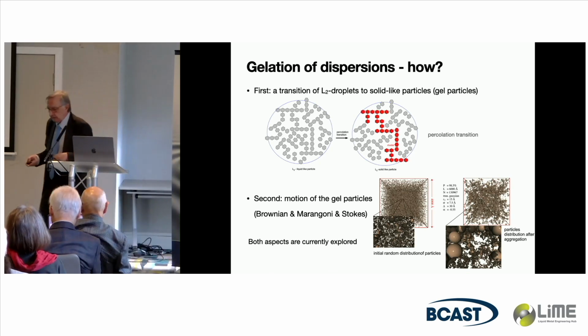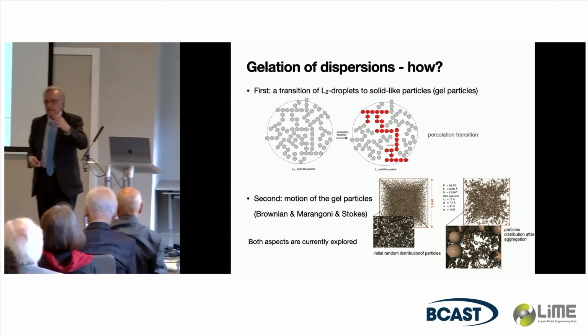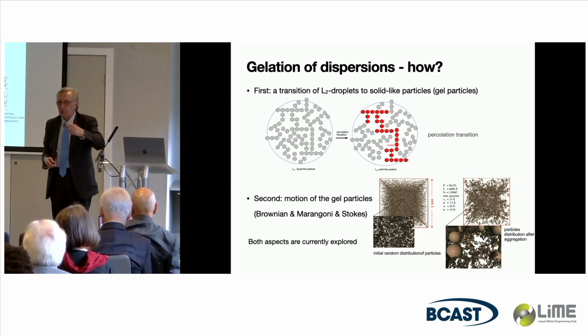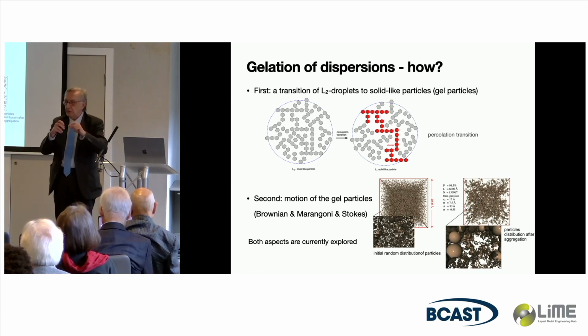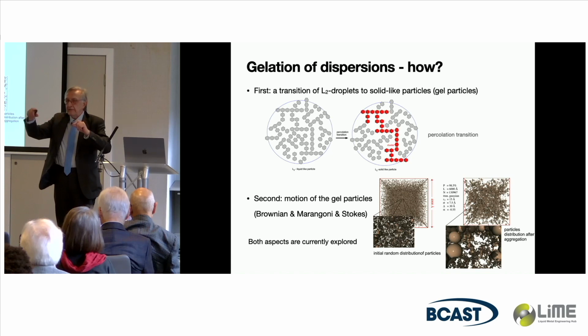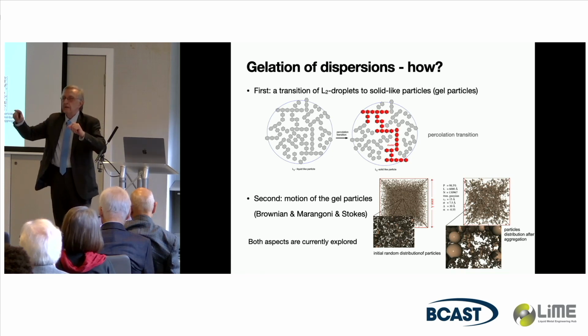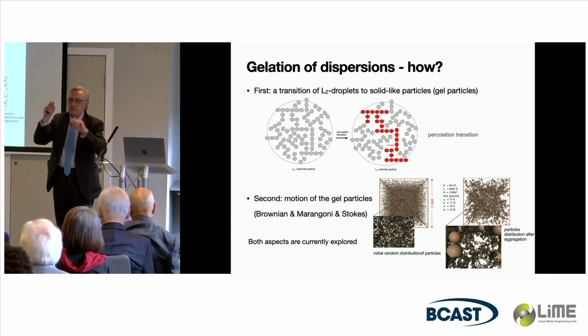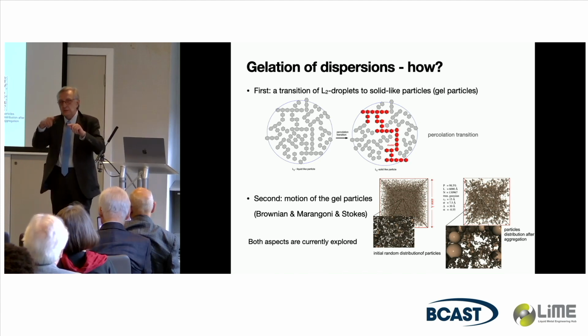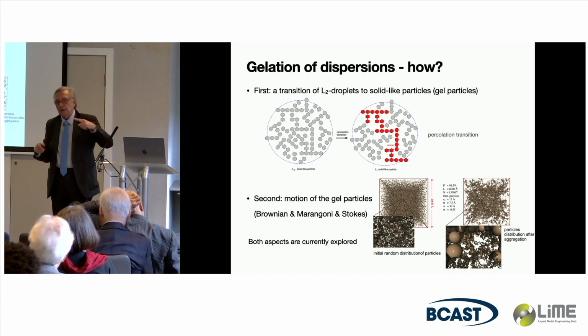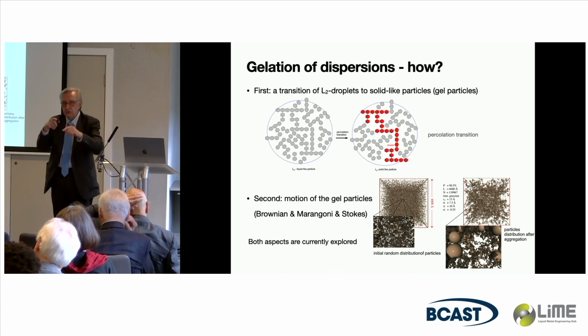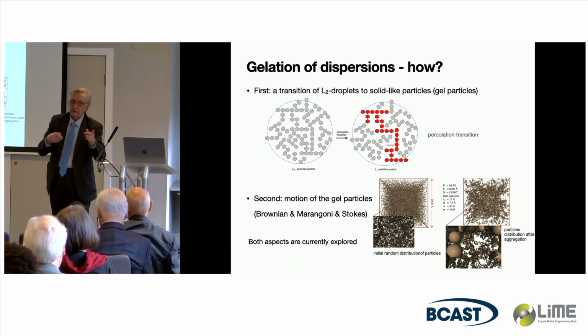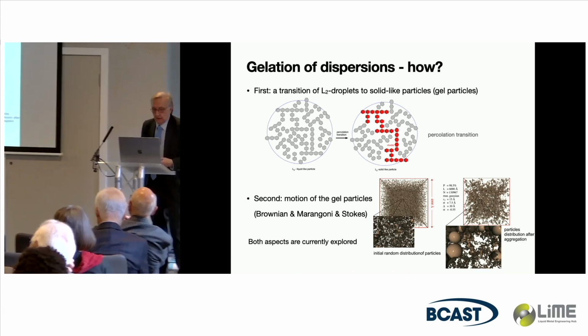Because we found out recently, and we have published a paper on that, that Brownian motion of droplets is different from Brownian motion of solid particles. Brownian motion of droplets can really make straight lines and not zigzag lines, depending on some physical parameters. And this would make a transition from diffusion-limited aggregation to reaction-limited aggregation, just due to the fact that the particles are not solid but liquid. So, okay.